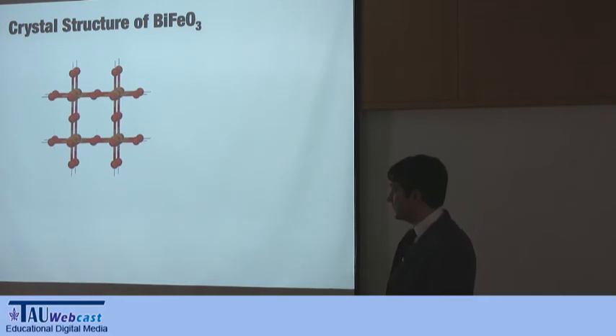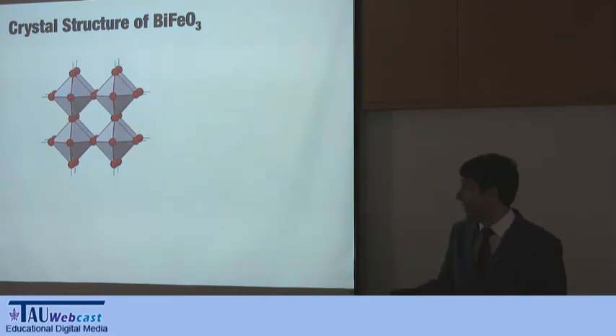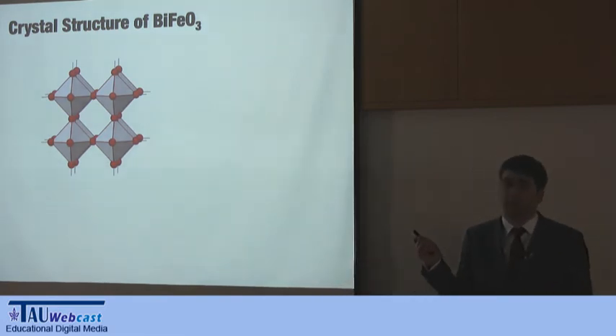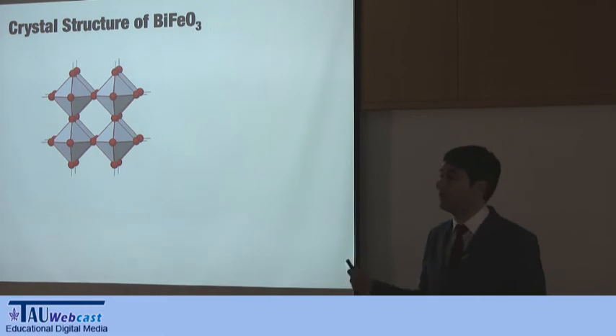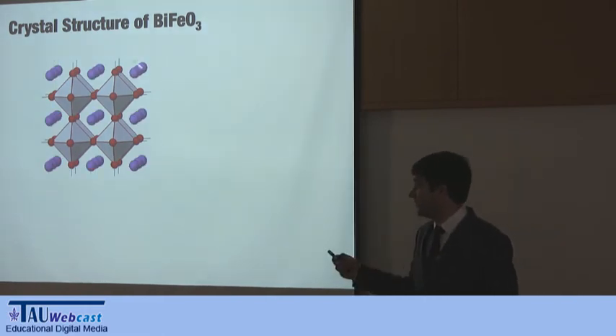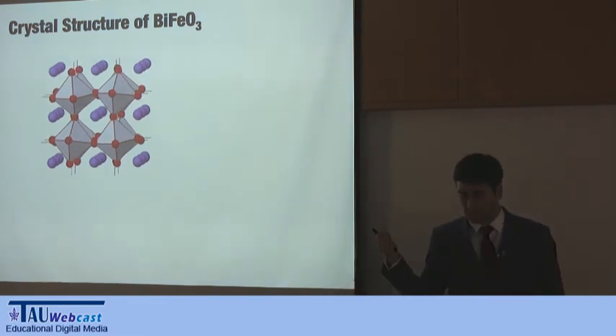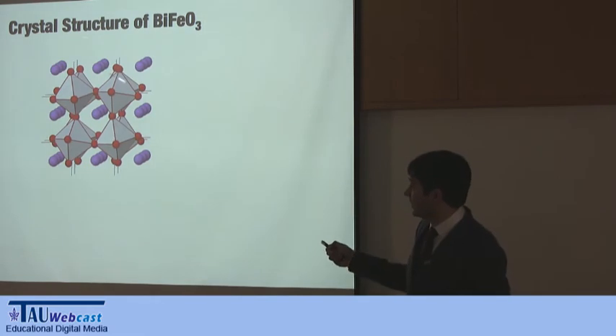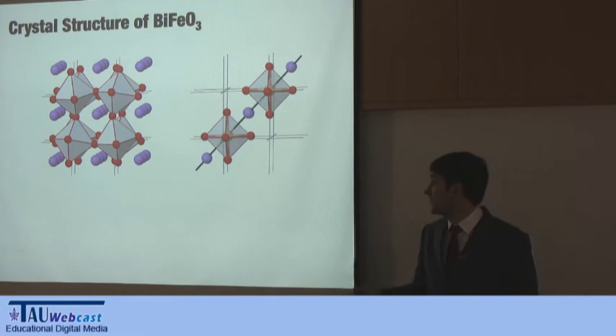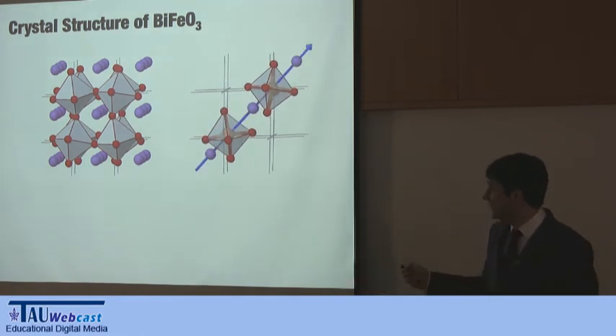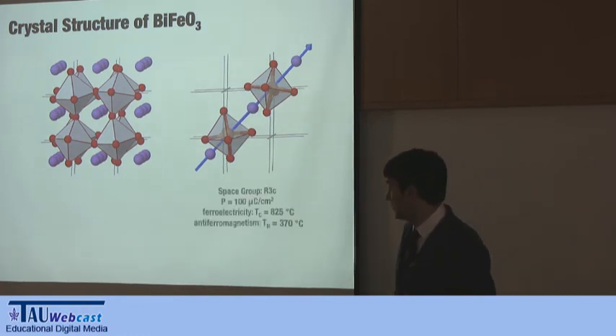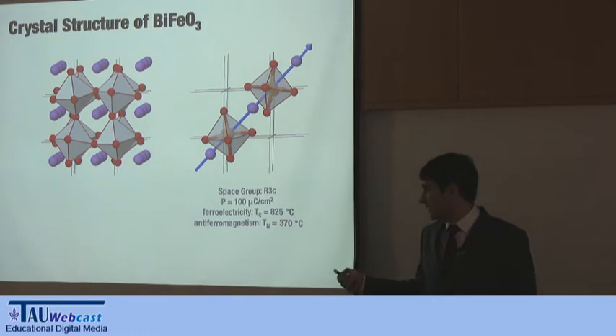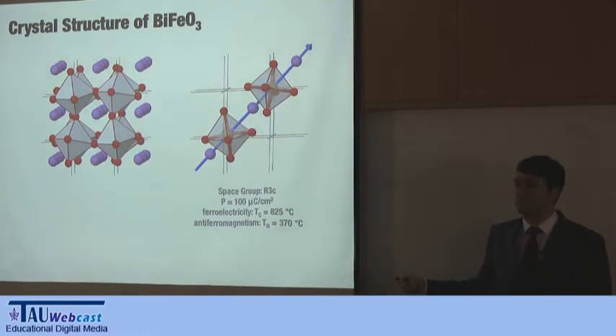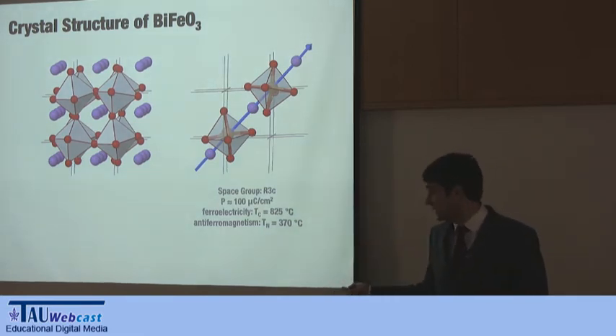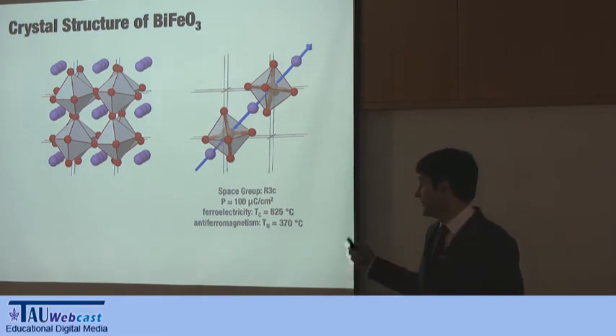So again, this is a perovskite structure with a big cation, with the irons there and oxygens between them, so you have octahedra surrounding them. Now, the distortion that occurs for this one is a bit more complicated than the one for barium titanate. Obviously you have the bismuth there, and what happens is that the cations displace along the 1-1-1 direction, and the oxygen octahedra rotate in antiphase. Here I removed some of the octahedra, so it's easier to see. So you get this displacement and that polarization. This is a rhombohedral lattice, as I said, with a high polarization. The temperature at which this becomes nonpolar is 825 Celsius, and the Néel temperature for antiferromagnetism is around 370.